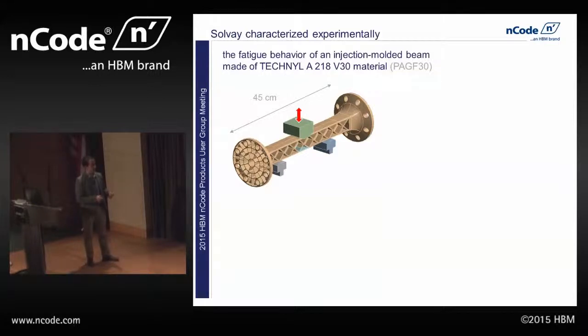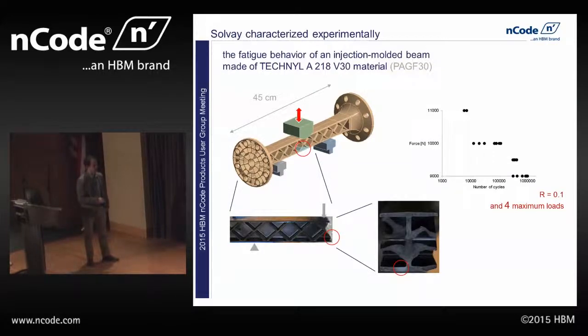So in this case, we're going to look at this beam made with a Technyl material. It's a PA6 nylon with 30% glass fibers. And we're going to put it on this 3-point beam bending test, and we're going to load it vertically. And basically, they're going to run this setup for 3 different loads and then determine the fatigue life of the part. And we went back and then looked at each individual part to understand where the cracks started and how this fatigue failure initiated.